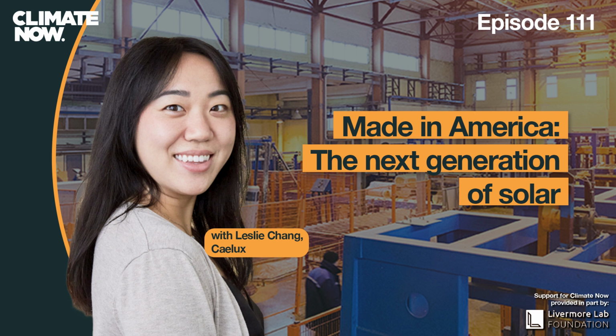30% greater. Okay. 30% greater, right? So first of all, your overall efficiency gains are so great, it doesn't really matter that you're not capturing quite as much of the silicon. But what we're finding also is that over time, perovskite, because it's being exposed to so much light, actually gets lighter in color. So the hypothesis is that down the line, as you're putting these enhanced solar panels out in the field, as the perovskite degrades, you're going to be able to capture more of the silicon. And also because silicon isn't exposed to such harsh conditions, it might actually preserve the lifetime of the silicon. That's the hypothesis. Interesting.